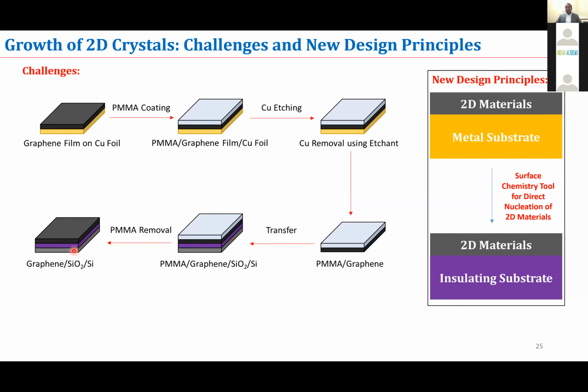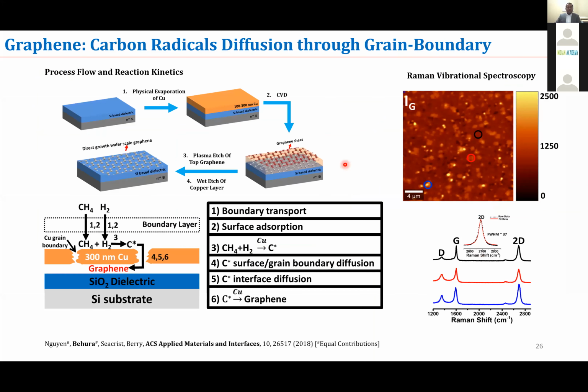measurements, as well as other device applications that are only possible if graphene can be placed on silicon oxide or any insulating substrates. So therefore, it's a complex process to transfer. So what I'm going to present now is how I was able to get rid of this transfer related process. I started thinking about some of the processes that can lead to formation of graphene directly on these insulating or dielectric substrates. So one such example is producing interlayer graphene on silicon oxide.